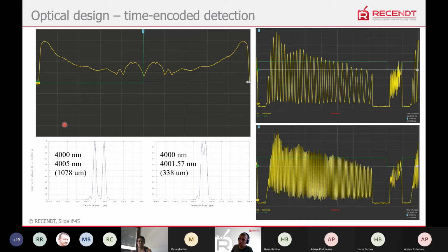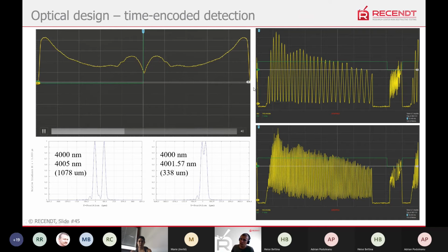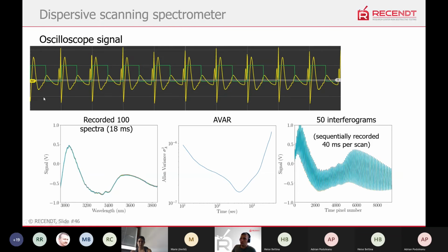For calibration I used spectroscopic calibration, and here should be a video of how it works. It's a live video, and I'm inserting different polymers inside. So it's not a calibrated spectrum. This is the sweep in one direction, and this is the sweep back because we used a galvo scanner. We could see the absorption lines of polymers that can be further employed to calibrate the system. This is how our signal on the oscilloscope looks like. This is for another source, but it's just to show it here.